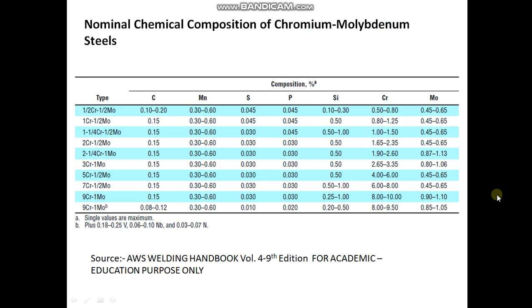The nominal composition of chromium-moly steels ranges from half-chrome, half-moly to 9-chrome-1-moly. The important alloying elements are chromium and molybdenum, and carbon is controlled to 0.1 to 0.15%, manganese to 0.2 to 0.6%, and sulfur and phosphorous are controlled to very low levels as they are impurity elements. 9-chrome-moly steel also contains small amounts of vanadium (0.18 to 0.25 wt%), niobium (0.06 to 0.1 wt%), and nitrogen (0.03 to 0.07 wt%).